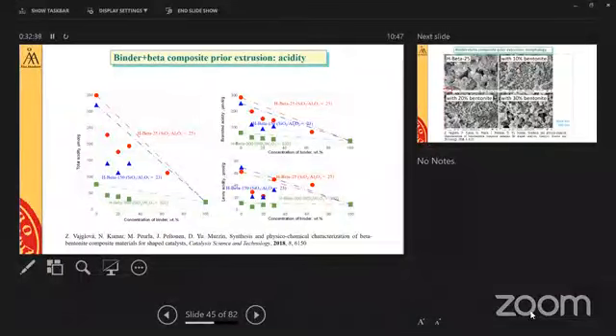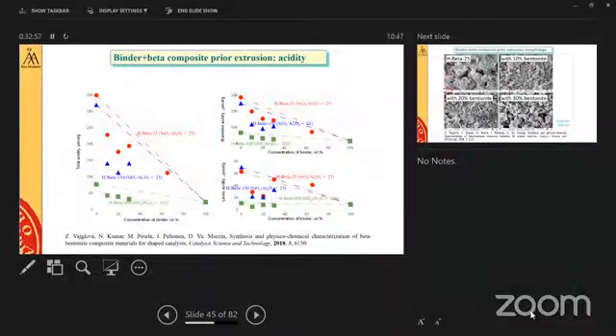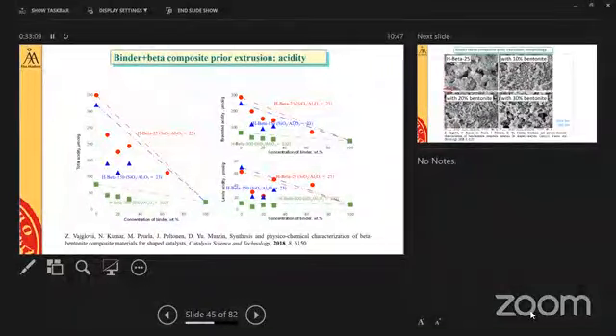Well, this slide is very busy. I will try to guide you through. Acidity of the beta zeolite, here with the ratio of silica to alumina 25. This is acidity of the neat binder. Okay? So one would expect that if we have a mechanical mixture made by this ball milling, then we will have just the acidity as a linear function of the concentration of the binder. That would be the expectation. In reality, it's not like that.